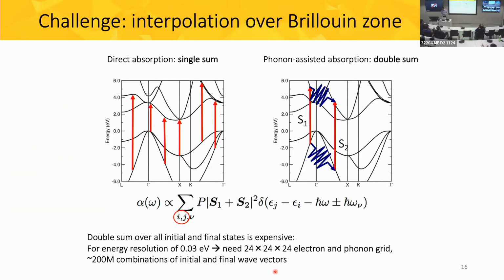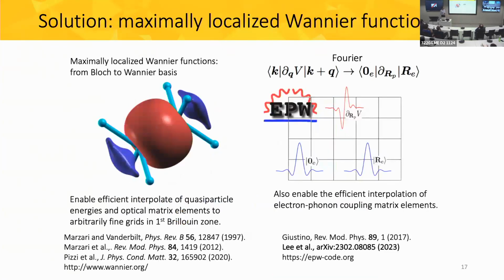So what do we do? We learn the method of interpolation, the method that Nicola pioneered in the 1990s and early 2000s, where basically we transform from the Bloch to the Wannier basis, and that allows us to interpolate the key quantities to arbitrarily fine grids in the Brillouin zone. And those are the electron energies, the optical matrix elements, but primarily the most difficult part, the electron-phonon coupling matrix elements, with a method developed by Giustino and others, and are now implemented in the EPW code.